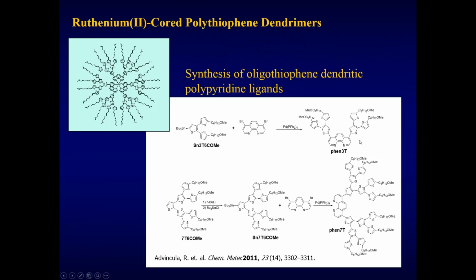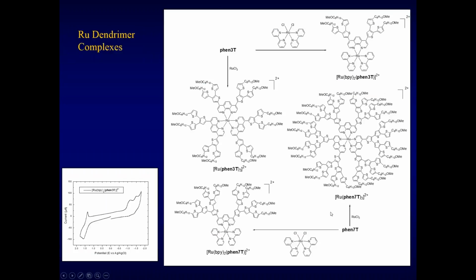Now what's interesting here is that although we've observed most of the energy harvesting properties, as well as their ability to shift the absorption, what's interesting is that by AFM, we observed that these dendrimers are capable of forming two-dimensionally packed, hexagonally packed structures as shown here. In this case, we've used AFM to observe this two-dimensional crystallization on a graphite surface, where the polymers are parallel side packed on the surface.